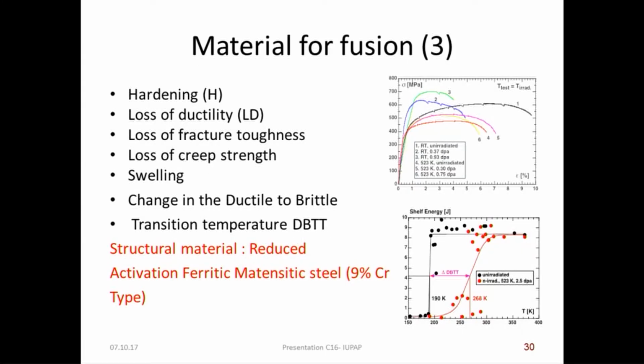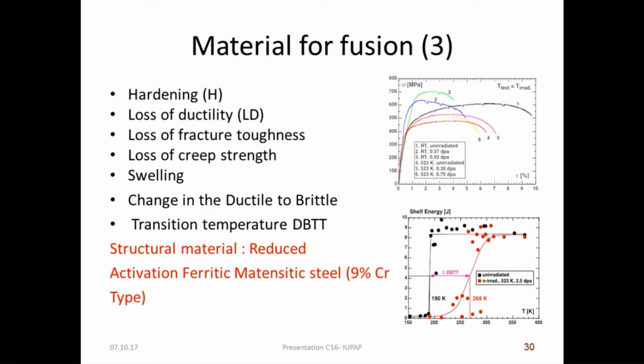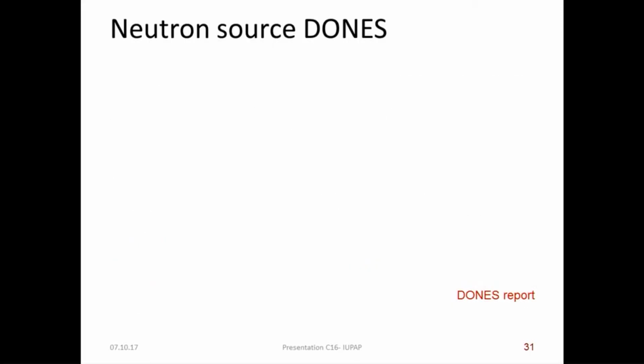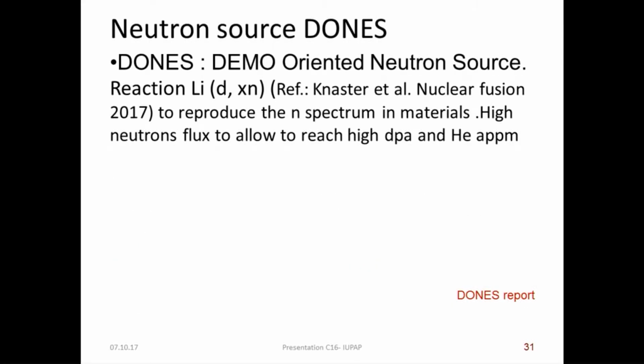And here, okay, we can skip this because you see here some typical metallurgical curve. There are two effects: the hardening, loss of ductility, loss of fracture toughness, loss of creep strength, swelling, and the second effect due to the embrittlement is the change in ductile to brittle transition temperature. So we need there a neutron source which is specific to produce 14 MeV neutrons.